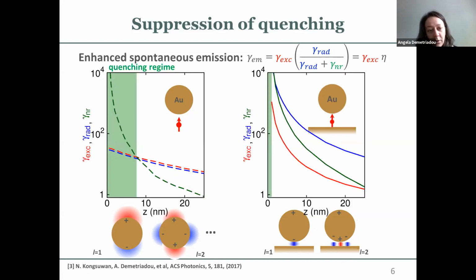When we were doing that work, we also measured the excitation rate of a quantum emitter in these two systems, which is the red line here, the dashed one for the isolated nanoparticle, and the full red line for the nanoparticle on mirror, and the radiative decay rate, which is plotted in blue. What we've seen for the isolated nanoparticle is that the excitation rate and the radiative decay rate were almost degenerate. There is a small difference, but they're almost degenerate. However, for the nanoparticle on mirror, they were quite different in value. And we couldn't quite understand why that was happening.